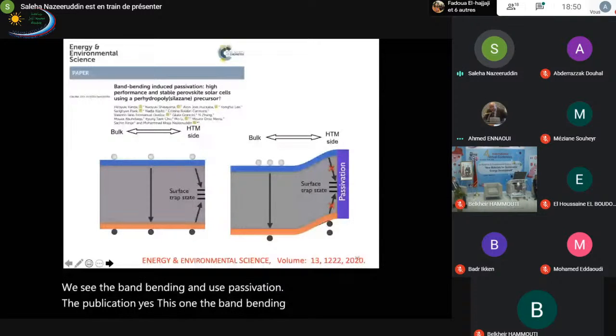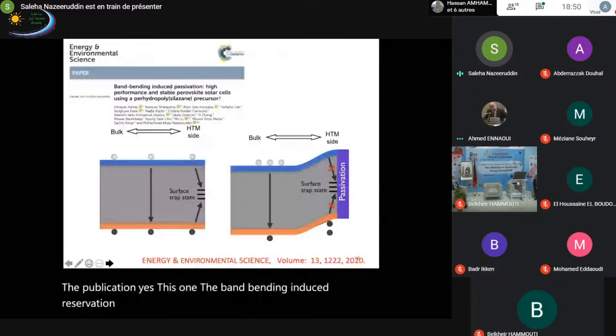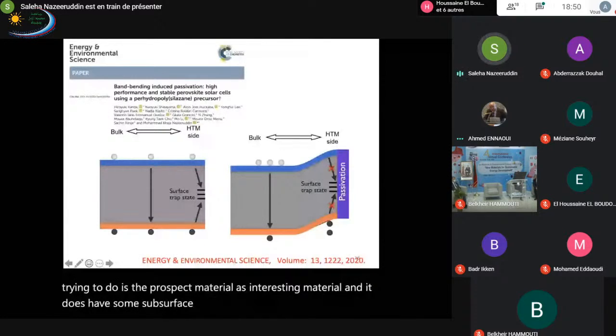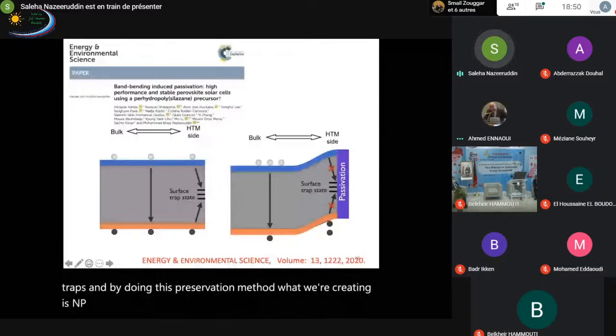Well, let me just discuss this one. What we are trying to do is, the perovskite material is an intrinsic material, and it does have some surface traps. So we are passivating these surface traps, and by doing this passivation method, what we are creating is an NP type of structure, where the bulk is intrinsic. On the surface, we have a P type of material. And this P type of material is only to the extent of 30 nanometers, as you will see from the data. Can you still see the slide? That's an Energy and Environmental Science paper.